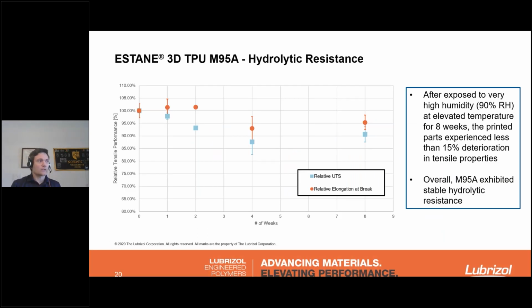And the last thing I want to talk about for performance attributes is the hydrolytic resistance of this material. This doesn't necessarily relate to a specific application. This relates more to the environment in which a lot of 3D printed parts happen to be used. A major issue for a lot of TPUs is that they might not be hydrolytically stable. So M95A was exposed to 90% relative humidity for 8 weeks with minimal to almost no loss in observed tensile strength. So we can consider the material hydrolytically stable. I know I used to live in Georgia and those summers were miserable. So I do understand how important the ability of parts to survive in increased relative humidity is.